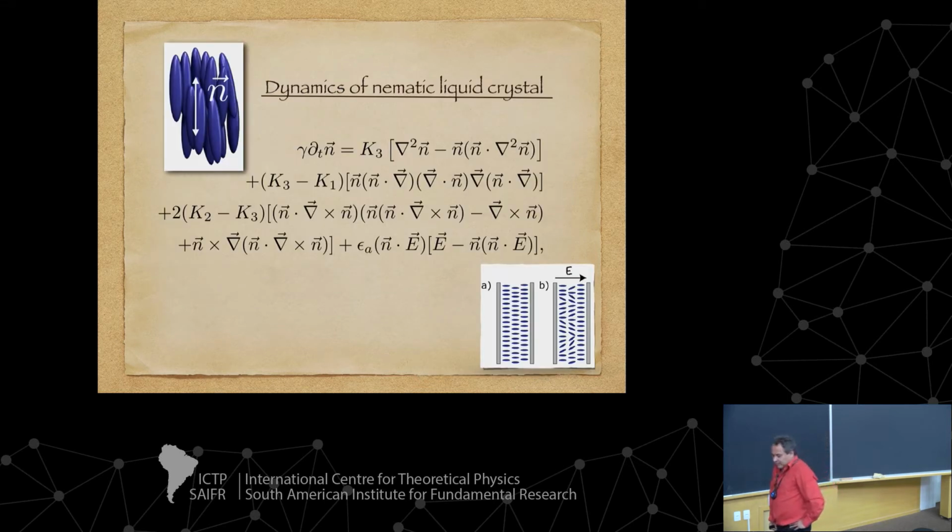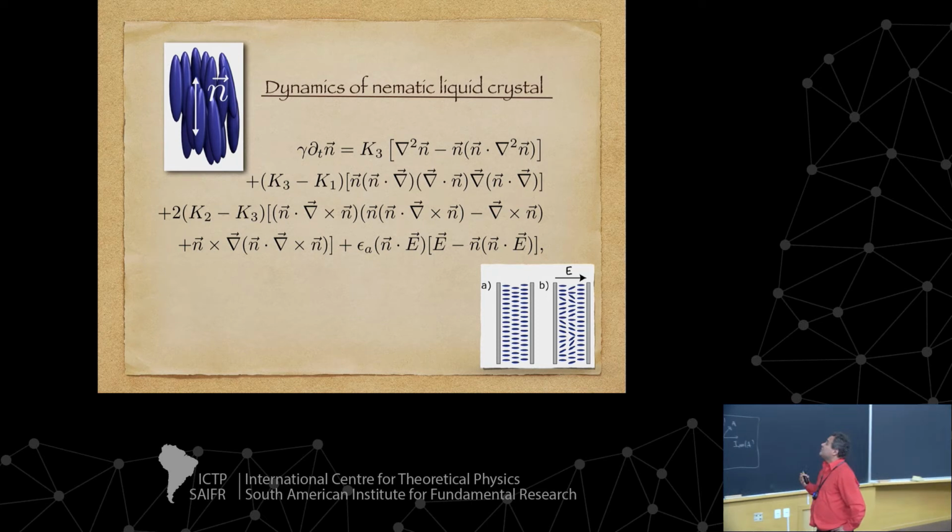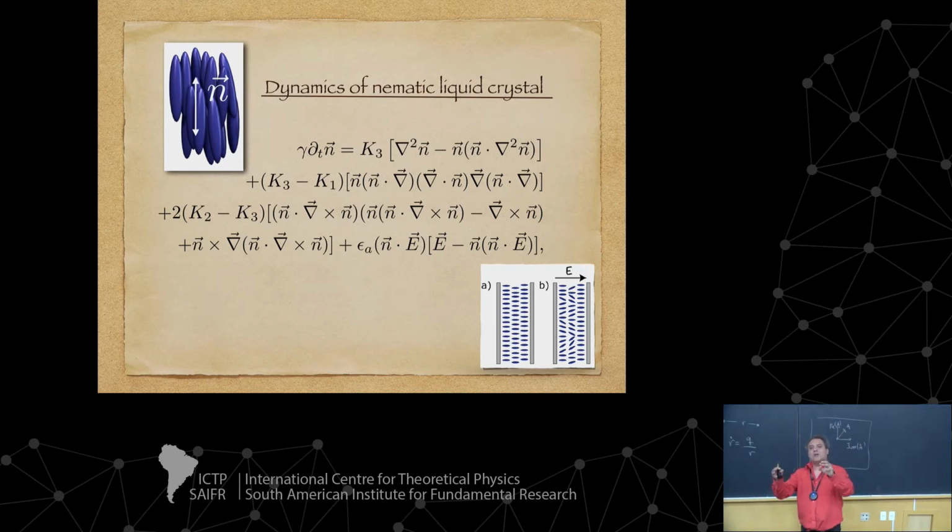Very good. But this general framework is possible to describe by the simple Ginzburg-Landau equation. The elasticity theory of the liquid crystal is here, which we call the Frank-Oseen energy; if you vary this energy, you obtain this equation. As a consequence of the material being very anisotropic, the molecules have different elastic constants. Normally when we use elasticity, if we consider a simple sphere, we have only one constant. But in this case, we have different constants for the different deformations of the liquid crystal: more or less splay, twist, and bend.